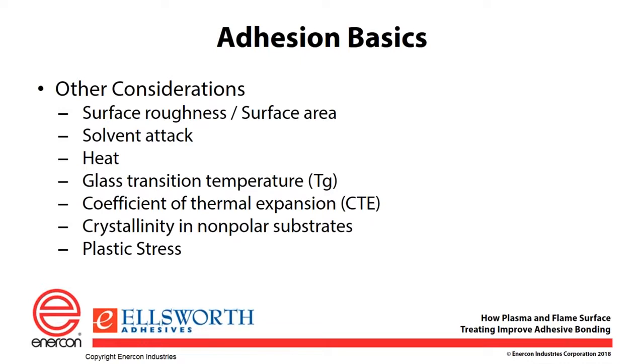I've already mentioned crystallinity of nonpolar substrates. The last thing to consider would be plastic stresses. When you have a molded part, stresses are molded into that plastic based on heating and cooling of the substrate. When you do things like a thermal cycling test, for instance, those stresses inside the plastic can cause the plastic to deform, and those stresses then can help create areas where you have bond failure.